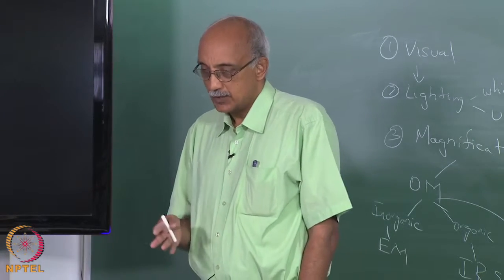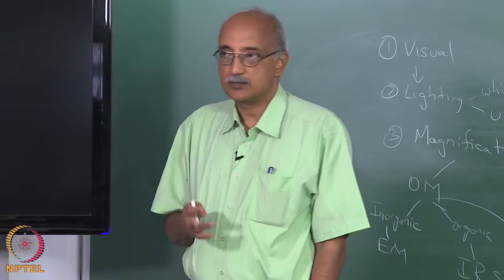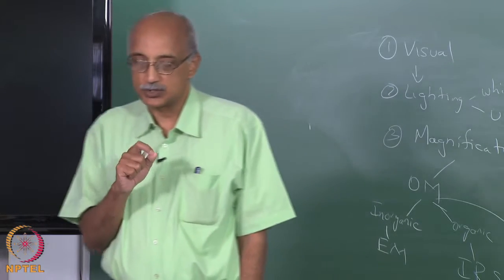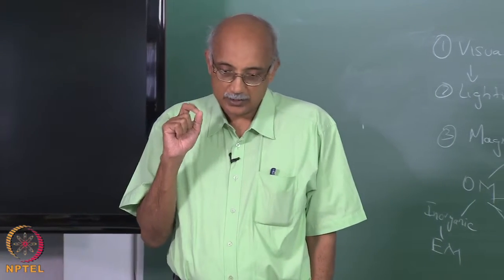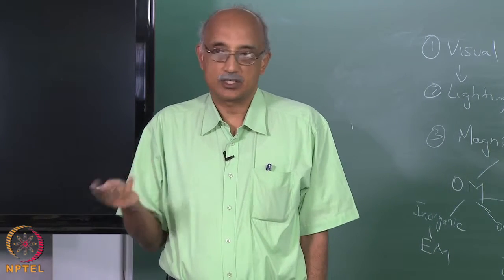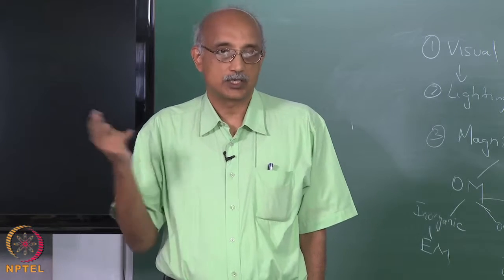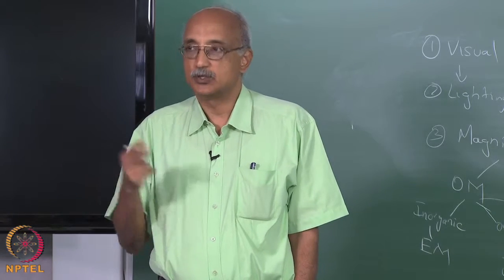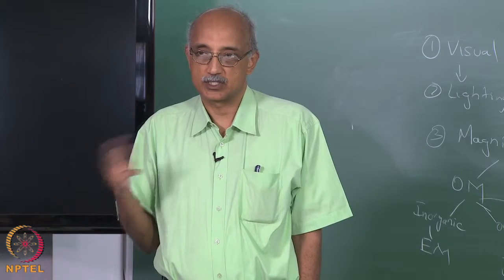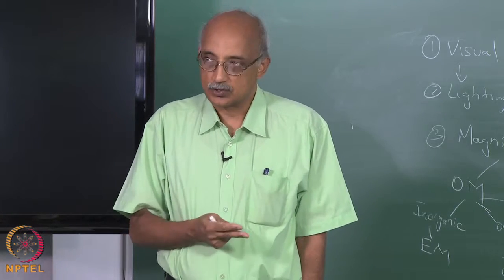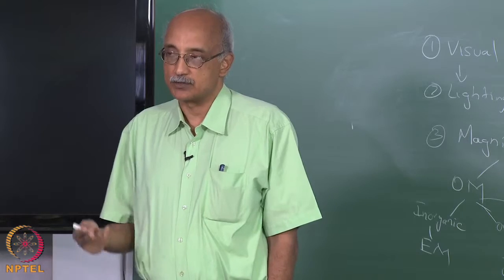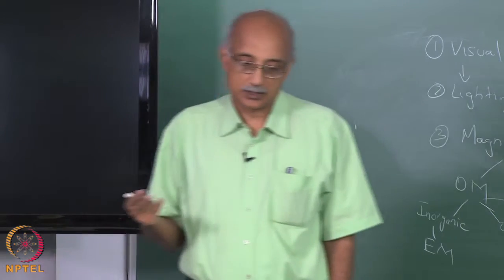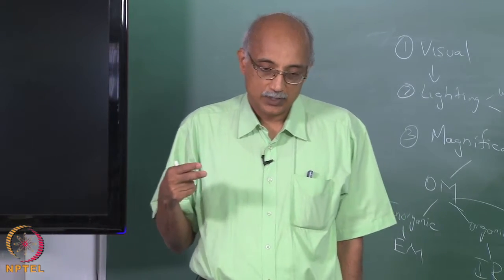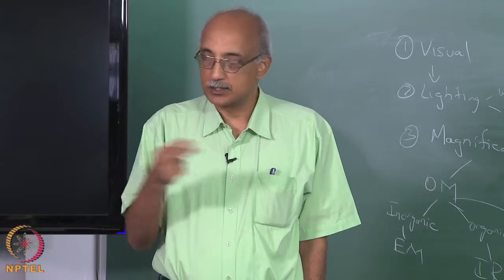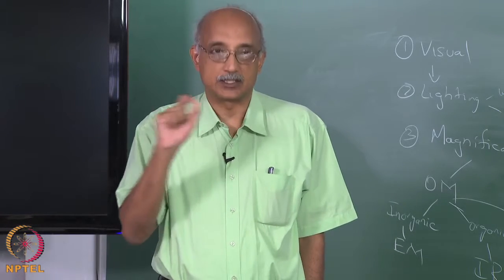So, the combination of SEM and TEM can certainly provide you with a much better resolution, but in order to get compositional information, SEM and TEM are not going to do it. So, you attach it to an EDS or WDS setup, which is energy dispersive spectroscopic analysis or wavelength dispersive spectroscopic analysis, which essentially use X-ray spectrometry of the signal to identify the actual elements that are present at that location.